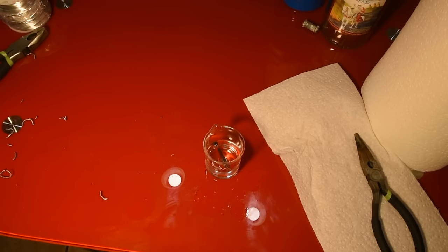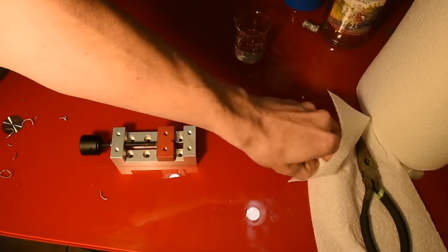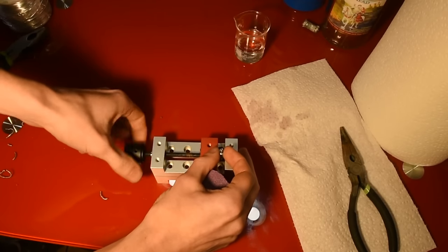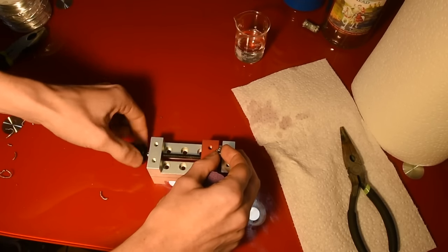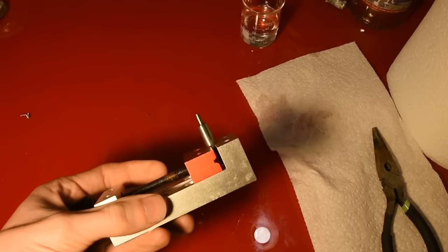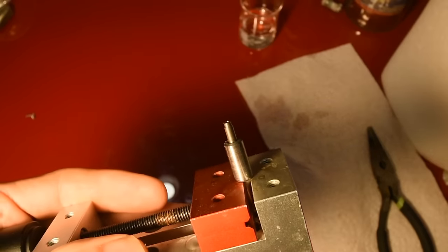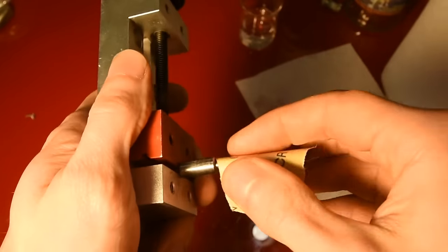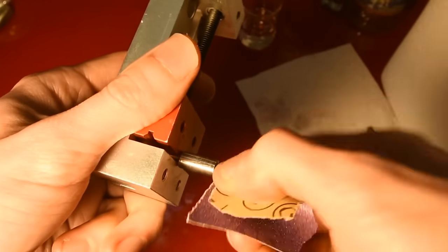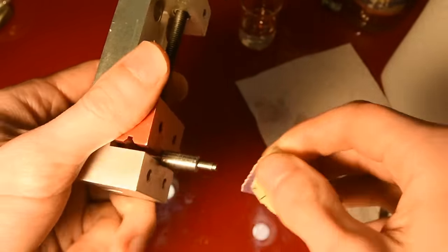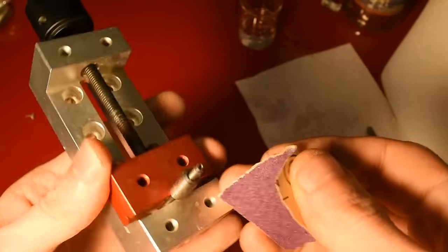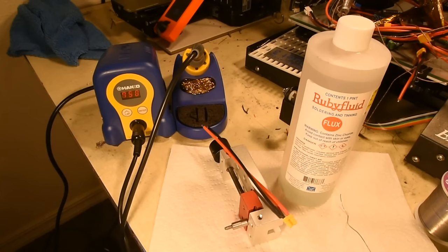We'll then clamp and gently sand the top electrode with 150 grit sandpaper to prep it for soldering. This is just to ensure that the surface has exposed clean metal and a nice low contact angle between the solder and the zinc chloride flux we're going to use.